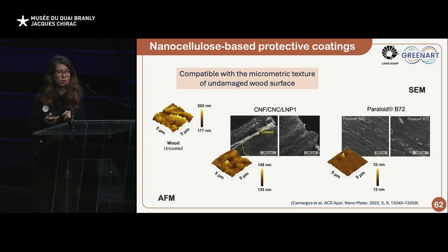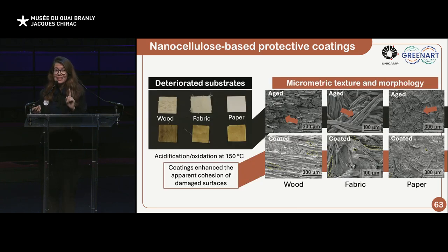And here is another interesting result. We can see here that when we coat the samples, a wood sample here, coated with the nanocellulose coating, we also have the micrometric texture and smoothness of the surface. But at the same time, when we consider aged mock-ups, deteriorated mock-ups, the application of the protective coating based on nanocellulose and nanolignin can even improve the cohesion of the surface, because when we have the aged mock-ups, the surface is quite uneven, it's quite damaged, actually. So the application of the coating can be very compatible, but at the same time can restore this cohesion of the surface.